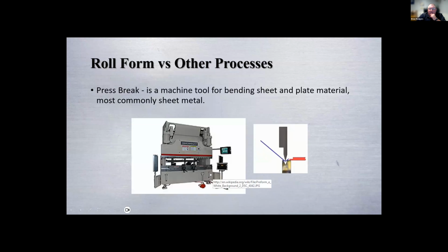So then when we get to press brakes, as you can see in the little video there, that's a perfect roll form part, because as you can see it's just doing it in one hit. The roll former will do it as it's rolling. Press brakes are very good when you're doing low volume. But when you get into higher volume and you want to run at a higher rate of speed, you're usually limited by your strokes, by the number of hits on the profile, and by the expertise of your operator.